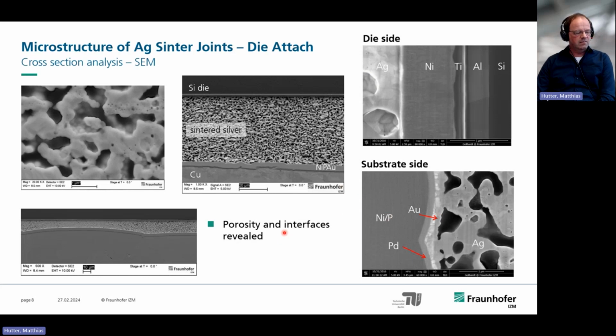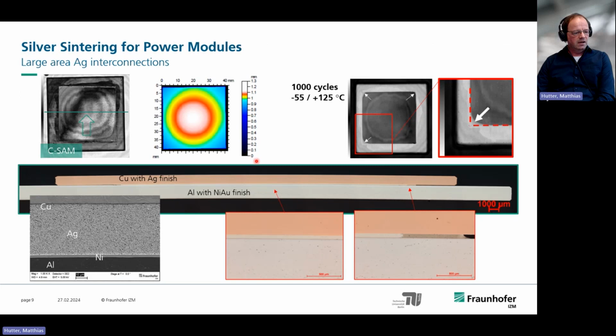It's very, very important to have these means in place in order to assure the high quality of the silver interconnects. Yes, you can also use silver sintering for large areas. So this is also more or less state of the art, to use silver sintering for the interconnects of the substrate to the cooler.